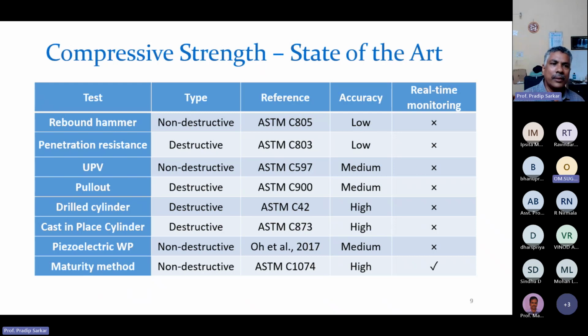Now, if you see, the rebound hammer is a non-destructive test which has a low accuracy. There is a penetration resistance test which is a destructive test that also has a low accuracy. The ultrasonic pulse velocity test and pull out test: UPV is non-destructive, pull out is destructive. They have a medium accuracy. Then drilled cylinder is a destructive test, or cast in place cylinder, again we break test them. They have high accuracy, but as we have discussed, we get a delayed result, or we get results for non-representative specimens. Then there are some piezoelectric methods and the maturity method. They are all non-destructive, but have a certain degree of accuracy.